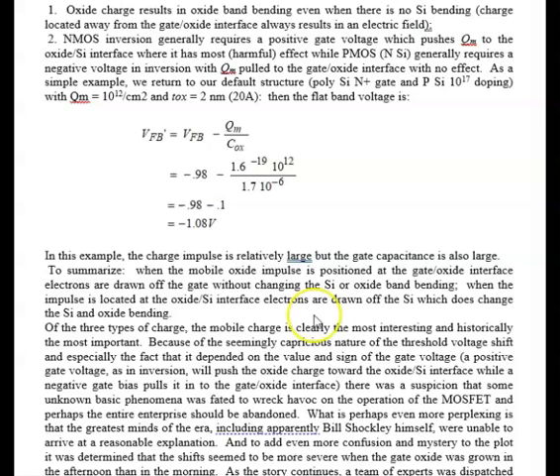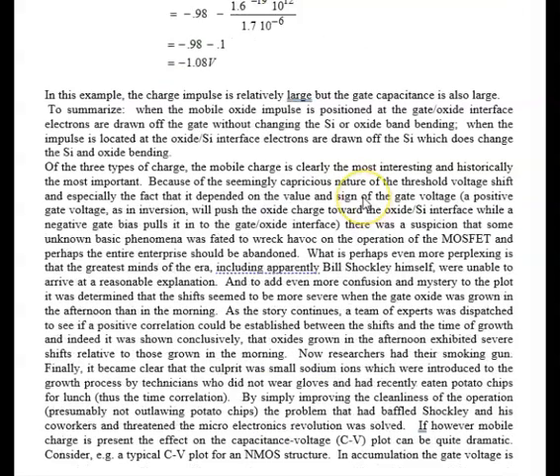And they narrowed things down to the gate oxide. The gate oxide was the thing that was really causing problems. Now, it's important to note that in those days they weren't talking about a gate oxide of 20 angstroms. They were talking about a gate oxide of 1,000 angstroms, perhaps, say, instead of 2 nanometers, 200 nanometers. Very thick gate oxides. And they at least narrowed it down, and they said the probable cause of all of these terrible effects, poor yields and lack of understanding, revolves around the gate oxide. And this was something that's even more perplexing today, because the greatest minds of that era, including the great Bill Shockley himself, and I say great with quotes because he had some personality issues, were not able to understand this.